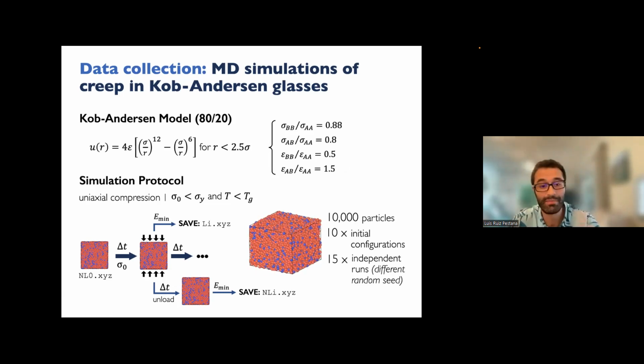Now, the simulation protocol is very simple. Don't even look at these details. We just subject the system to uniaxial compression. So the parameters here are an applied stress, which we make below the yielding point, obviously, and the glass is at a certain temperature, which is also well below the glass transition temperature. We do that because we want to study creep and we want to study the glass dynamics. All right, so these are our simulations. Yes, uniaxial compression of these systems.